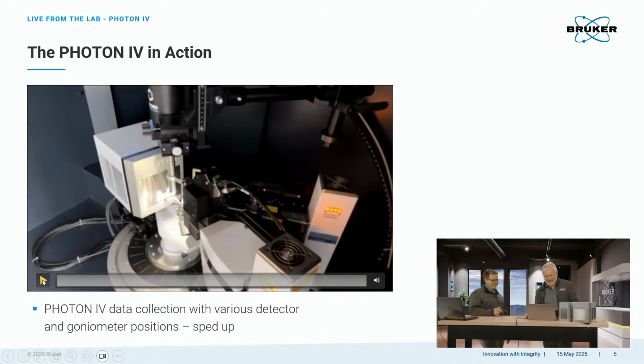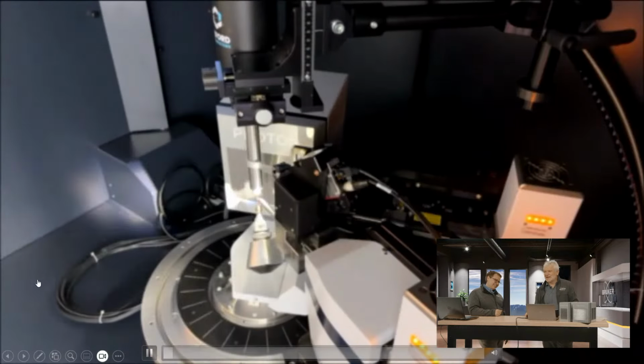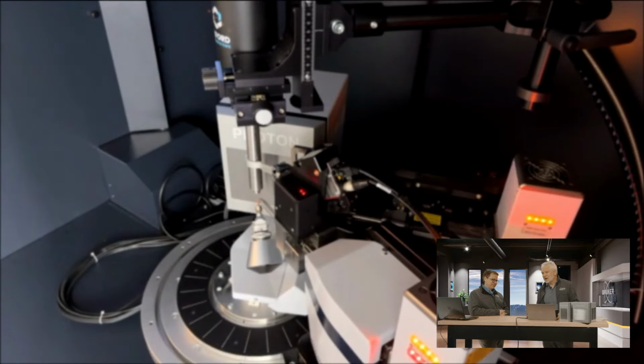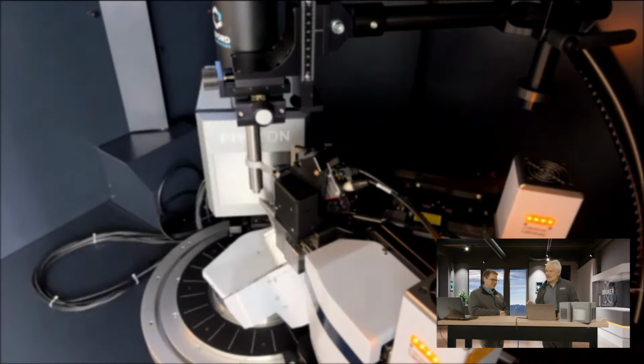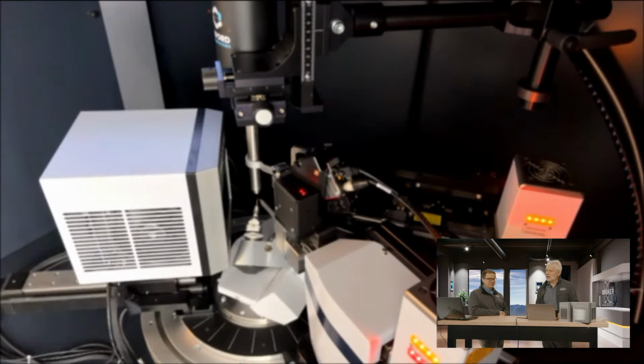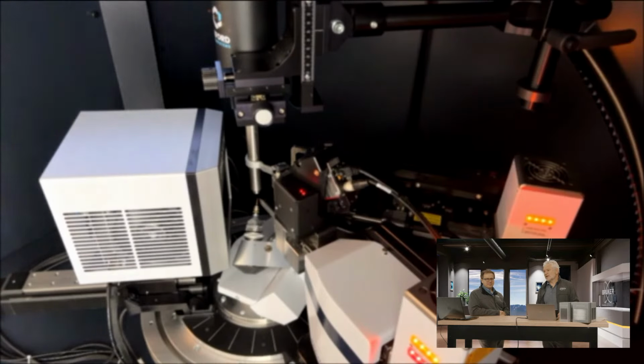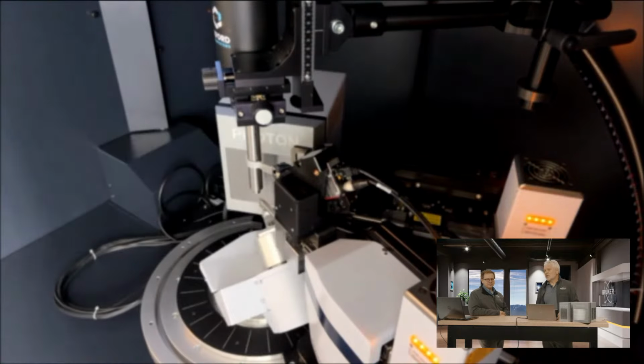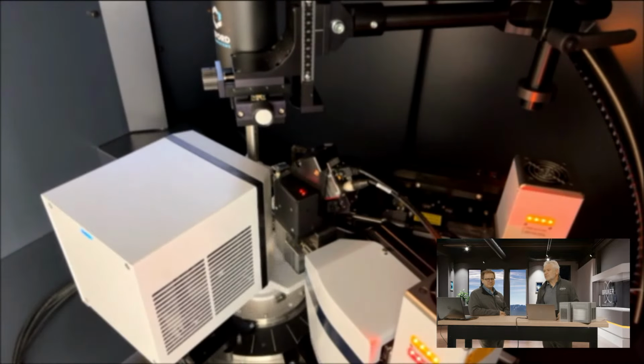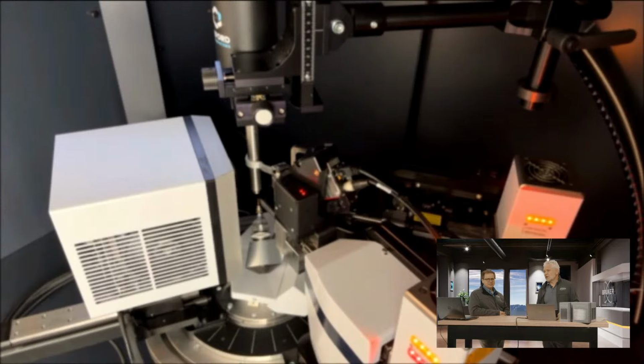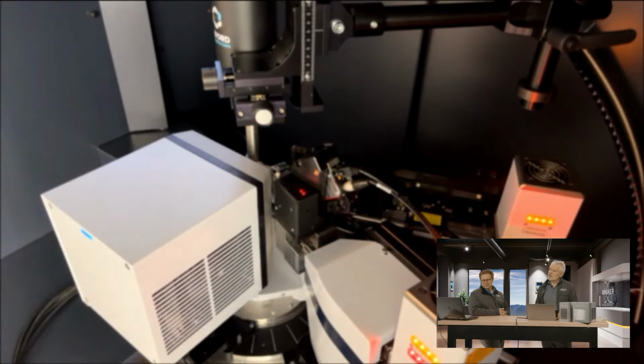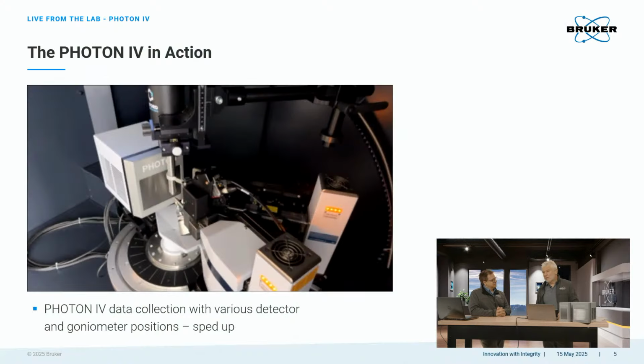So here I have a really short video that just shows you how it's implemented in the instrument. It's a little bit out of focus. It's a video taken from a webcam inside an enclosure in Karlsruhe. I think I sped this up by 30. This is a data collection with copper, where you need to go to very high resolution diffraction angles to get to atomic resolution. You see how the detector moves around. It's optimized, and that's why it makes sense that you have this tapered bezel, because you want to get as close as possible to your incident beam to be able to collect data to about 155 degrees in 2 theta.